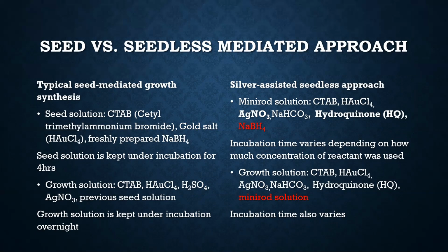The high uniformity synthesis in this article involves adding silver ions, or silver nitrate, to the seed synthesis, which helps with the one-directional growth from the beginning, resulting in a rod instead of sphere formation in the seed solution.